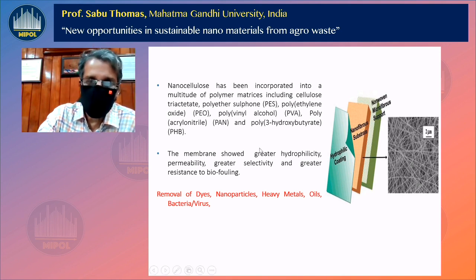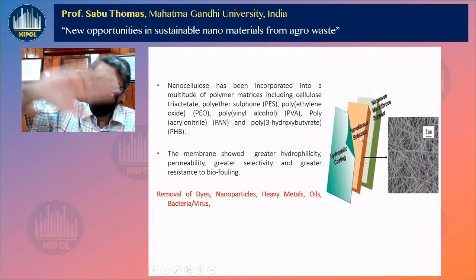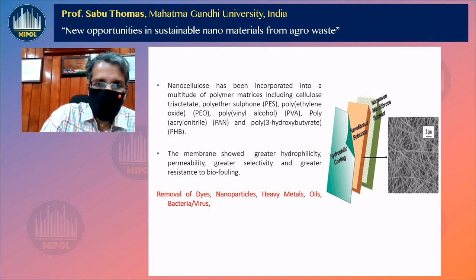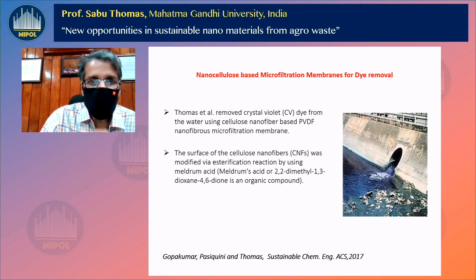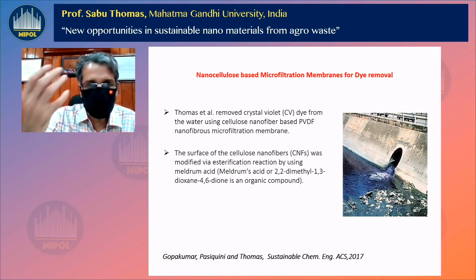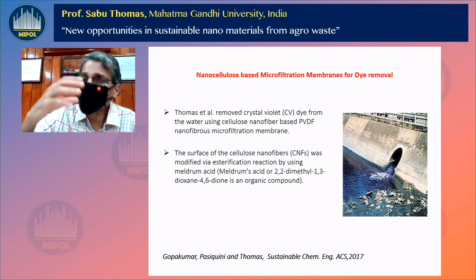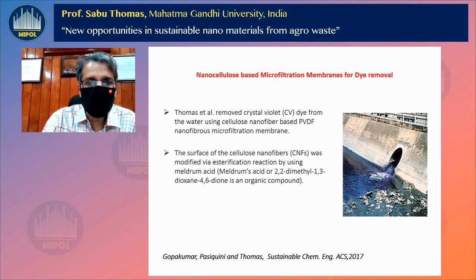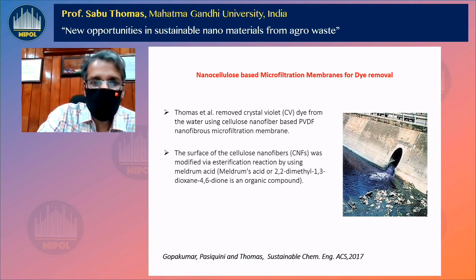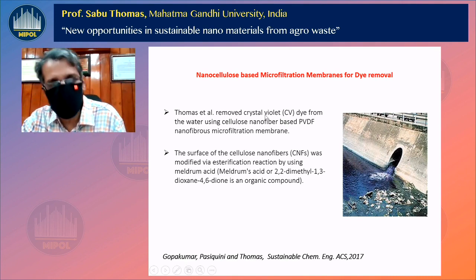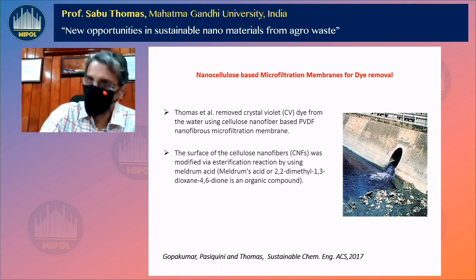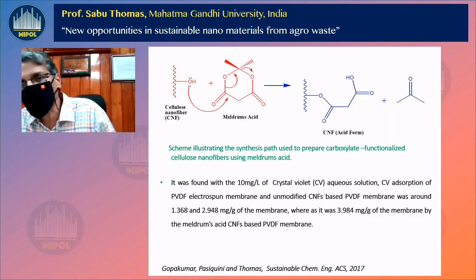So we thought of modifying the commercial filters. What we did is we gave a nanocellulose coating on the surface of the commercial filter to remove dyes, nanoparticles, heavy metals, bacteria, and viruses. Probably you all know that water is increasingly contaminated with different types of dyes, particularly coming from the textile industry. Textile industry uses lots of dyes. And we picked up some of them. One dye we tried to remove was crystal violet dye, which is very much used in the textile industry.